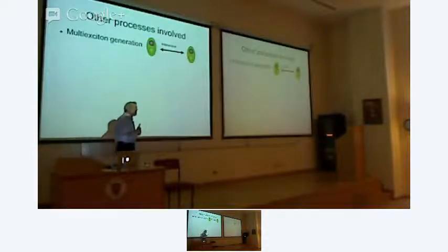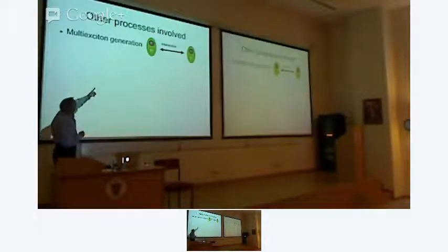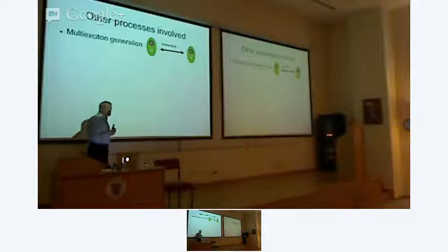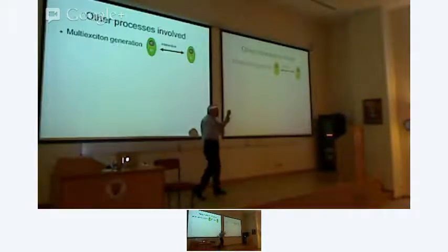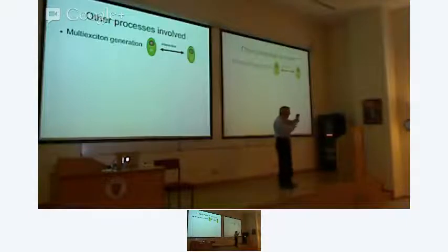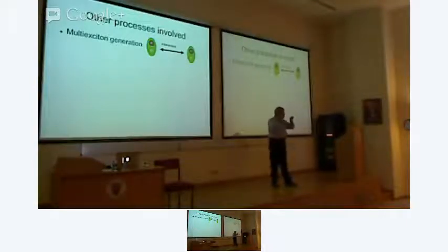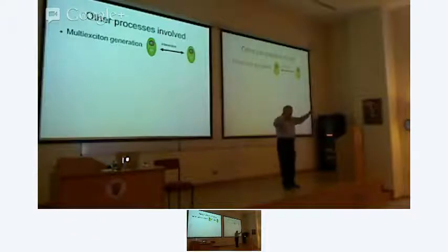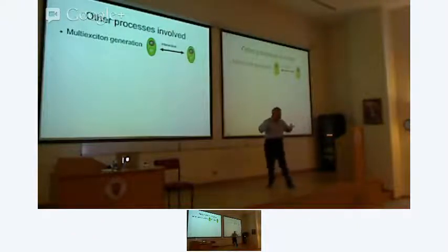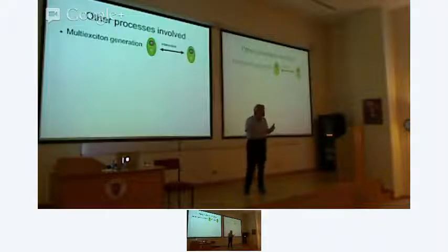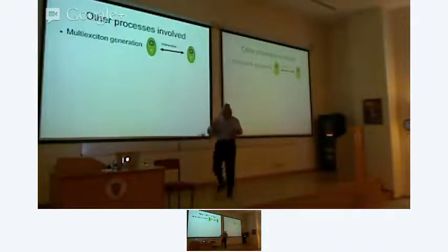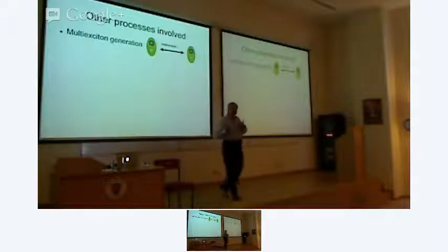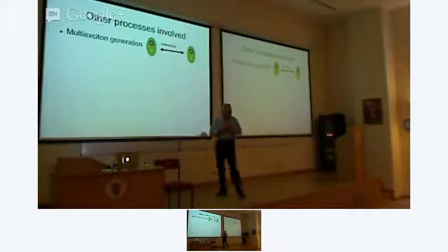There are lots of things that can happen once these excitons start moving around. You have things known as singlet fission, where you can create triplets. This is actually a very interesting process. We have only started to study it. So you've got one excitation, okay, that is a singlet excitation. That singlet excitation can actually be transferred to two molecules in the form of triplet excitons, okay. And those triplet excitons can then dissociate, producing two electrons. So you can use one photon to get multiple electrons. If you did that, your efficiency would be doubled. Okay? That's the whole point, is to be able to take advantage of the subsequent decay processes that are in these materials in order to make these materials more efficient.